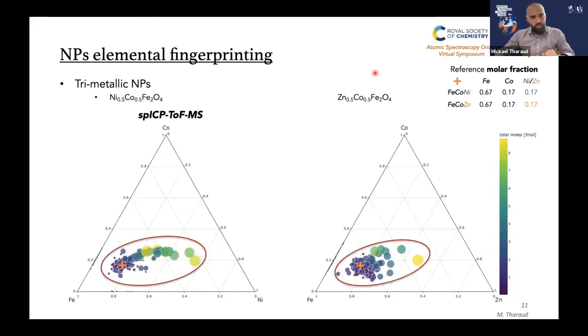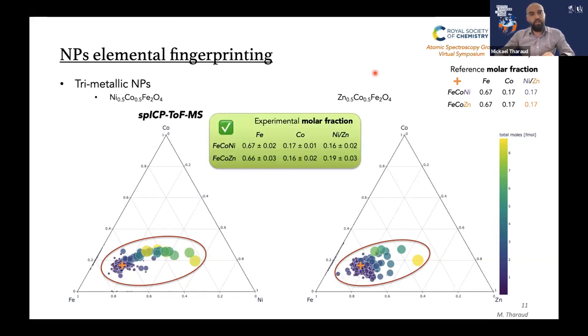So if we go back to our ternary diagram showing the cobalt, iron, nickel, and cobalt, iron, zinc composition, we calculated back the experimental molar fraction for iron, cobalt, nickel, or zinc. And as you can see here, those results are in perfect agreement with the reference molar fraction that was given by the manufacturer.